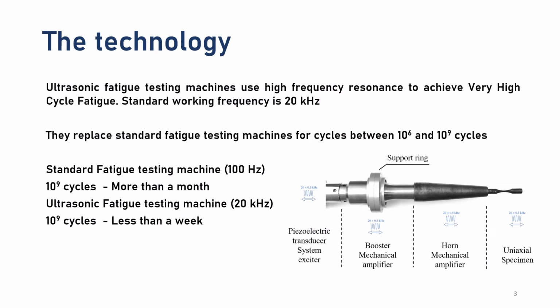Ultrasonic fatigue testing machines use resonance as a way to apply high-frequency fatigue. The objective of these machines is to study the very high cycle fatigue regime. This is established between 10 to the power of 6 and 10 to the power of 9 cycles. Here we have the tension compression machine, where we apply the piezoelectric transducer that has as a standard 20 kHz. Then it uses a booster and a horn that amplify the displacements coming from the piezoelectric transducer and induce the resonance of the specimen, which has the ability to have a high enough stress amplitude in one fatigue testing region, its center.